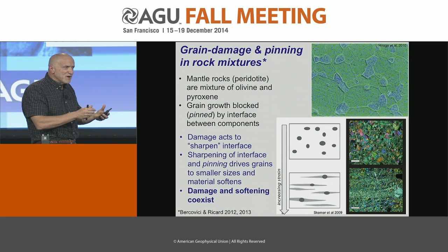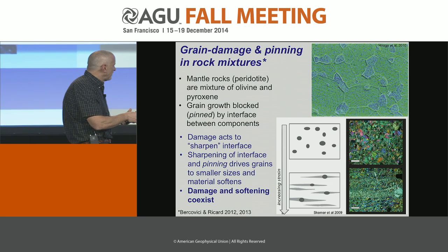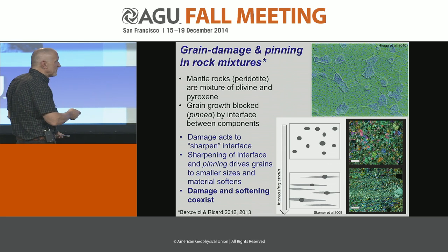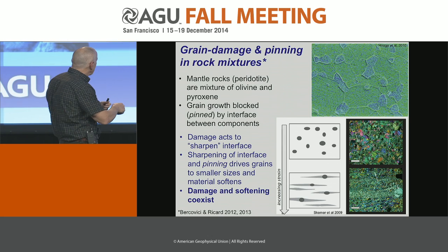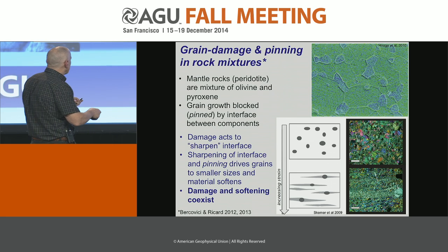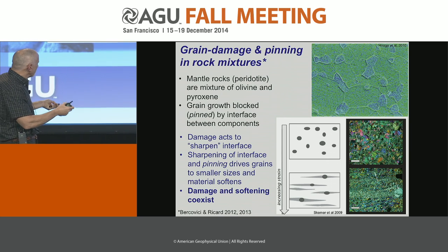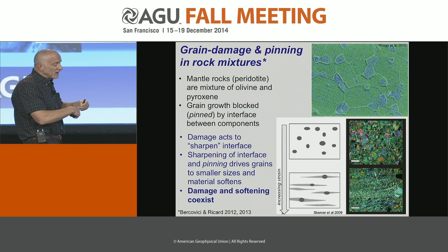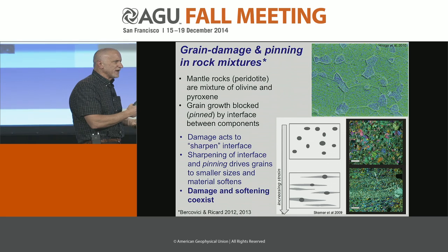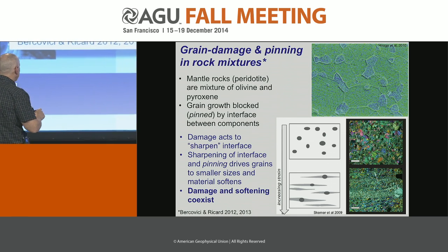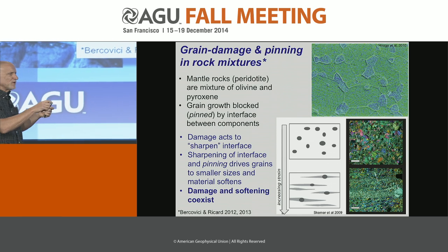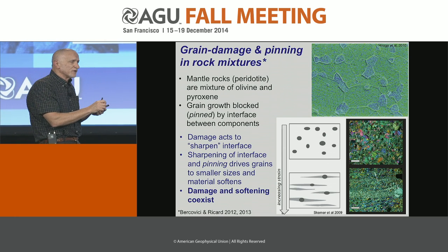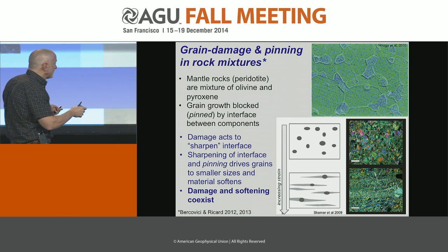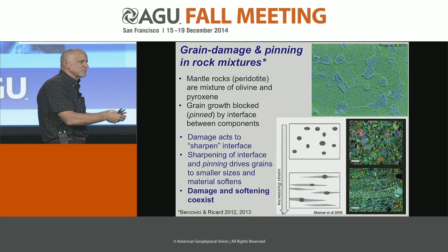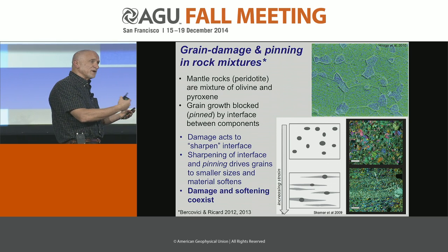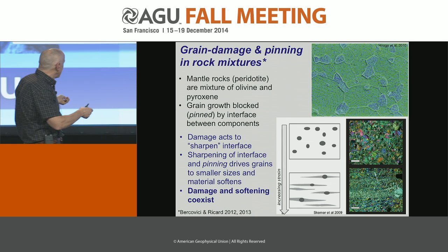If we damage the system by deformation, this is sort of where the theory my colleague Yannick Ricard and I have been chasing for a while. If we damage the system, not only can we perhaps drive some dislocations in the grains, but we'll also sharpen the interface, say, between the gray and the white, from a nice drawing from a paper by Phil Skemer and Greg Hirth and others from a while back. We'll damage the interface, or we'll stretch and mix and contort the interface between them and cause smaller pinning bodies. I'll get into this better explanation in a minute. So we drive smaller pinning bodies that hold the grains at smaller sizes, or even drive them to smaller sizes into diffusion creep that allows us feedback. So I'm basically damaging pinning bodies that then drive the grains to smaller sizes, and then they're softer because they are in a small grain size state that allows this diffusion creep to occur.